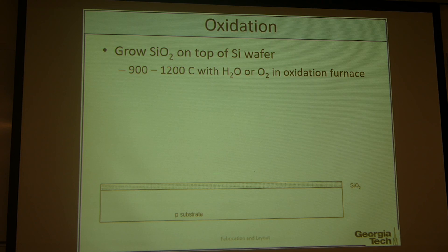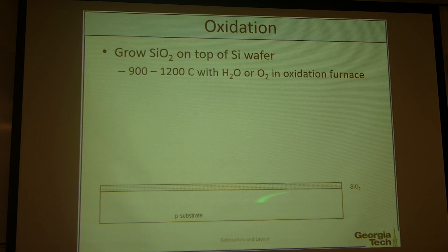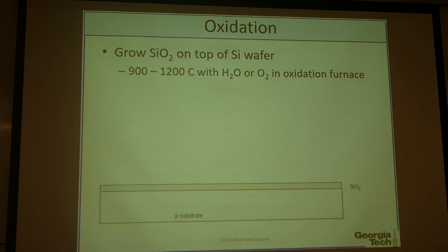To make the N-well junction in the pre-designed location, we need SiO₂, which will block the atoms from going through the silicon area. We grow the silicon dioxide on top of the silicon wafer at a temperature of 900 to 1200 degrees Celsius, with water vapor, oxygen, in an oxidation furnace.